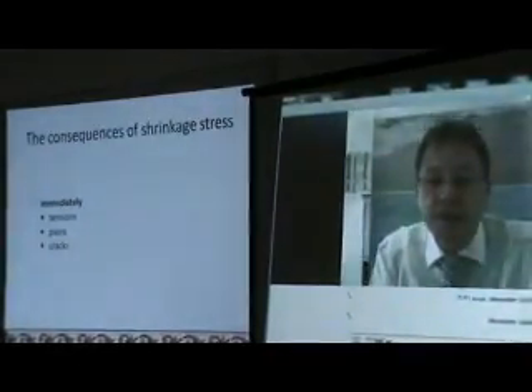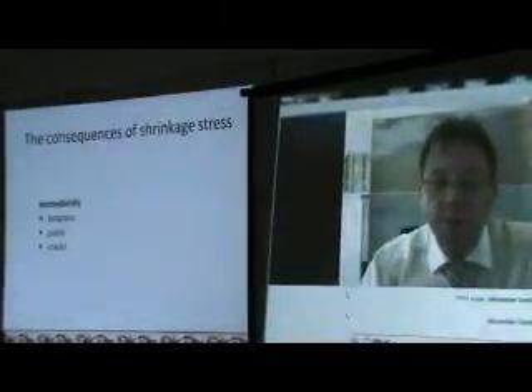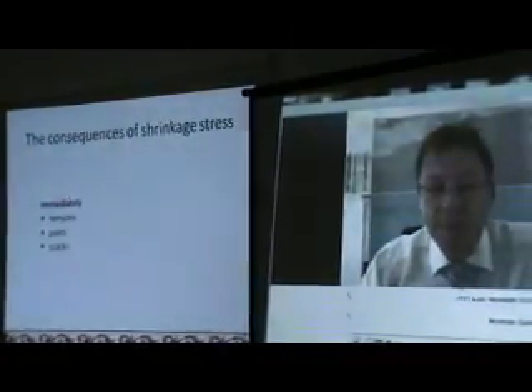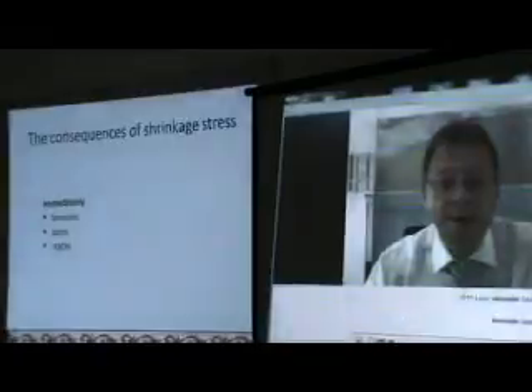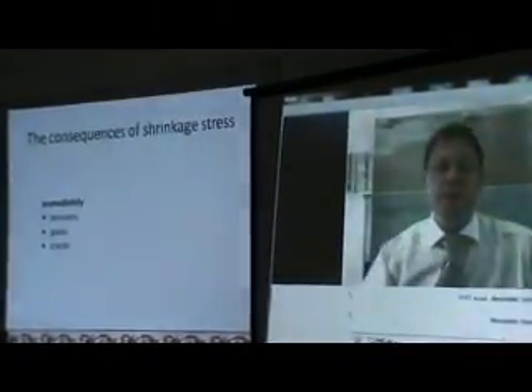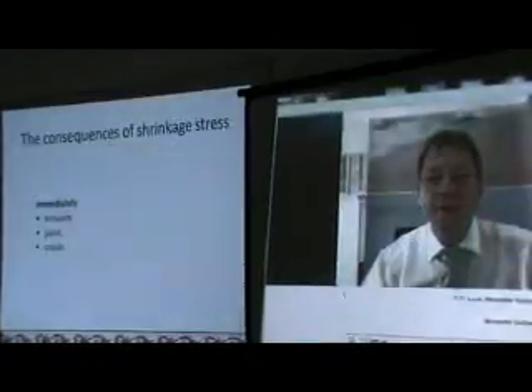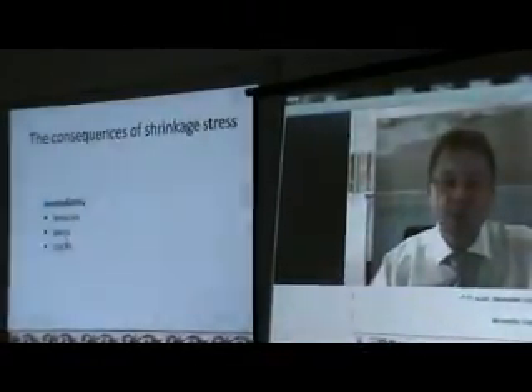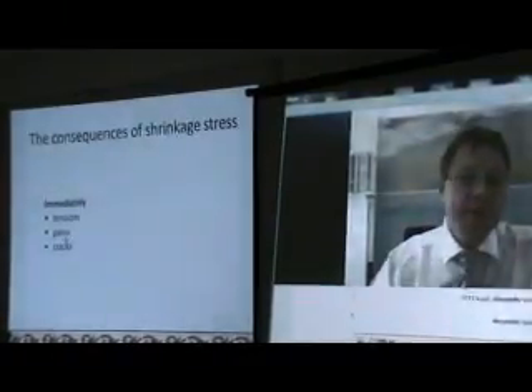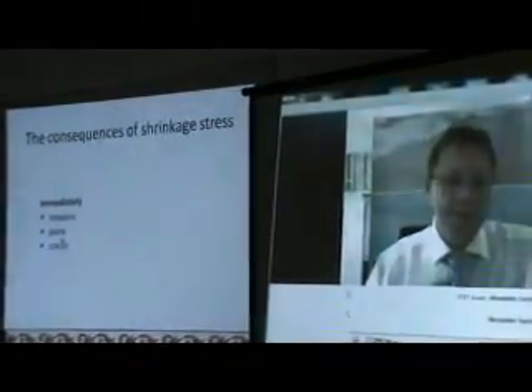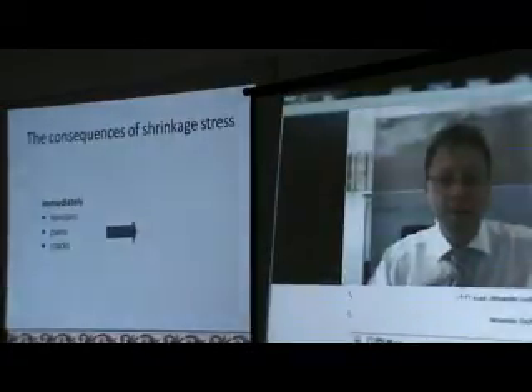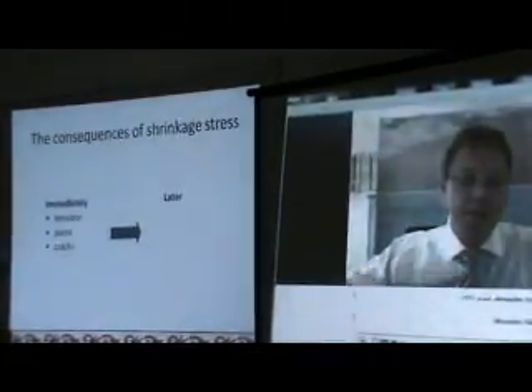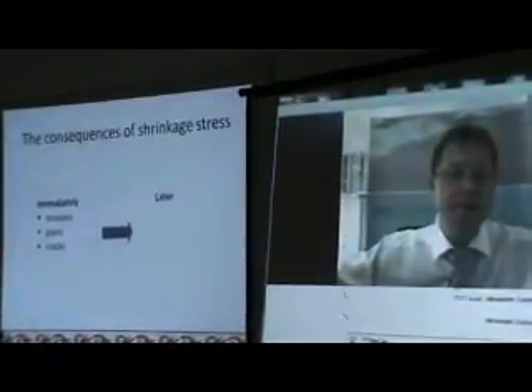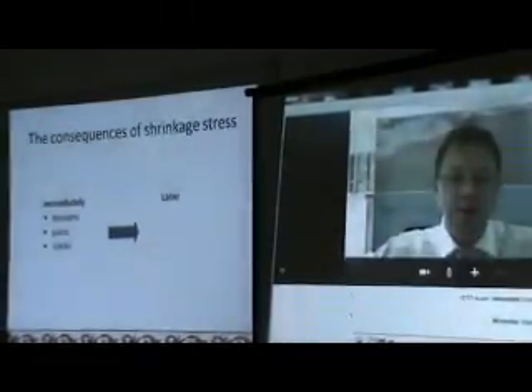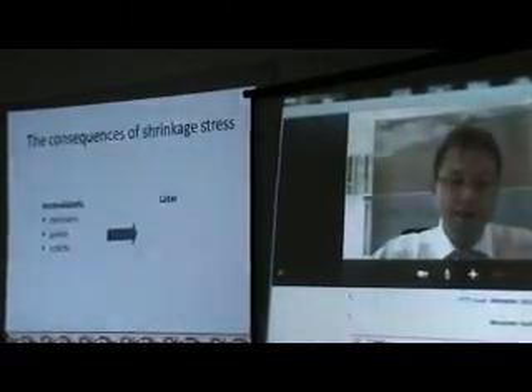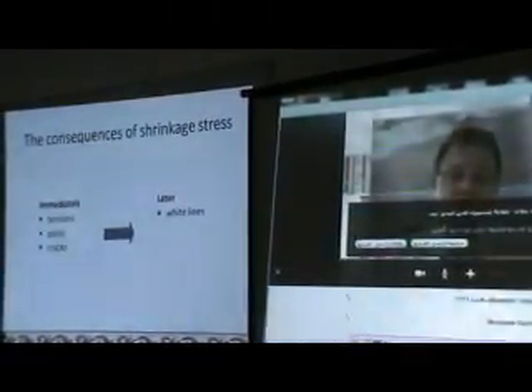You must understand that shrinkage stress builds up over a time of 30 minutes. So that means you may have already finished the treatment with your patient, but the patient will have pain only later, due to the fact that the shrinkage stress builds over a certain time. It's not that shrinkage stress is there immediately and then it is done. It builds slowly up over a period of 30 minutes and then it stabilizes, and then the stress, this tension, is stable as long as the adhesion will be efficient.